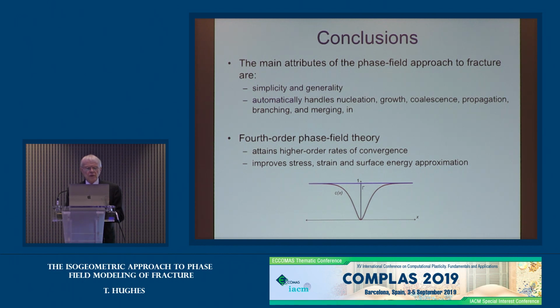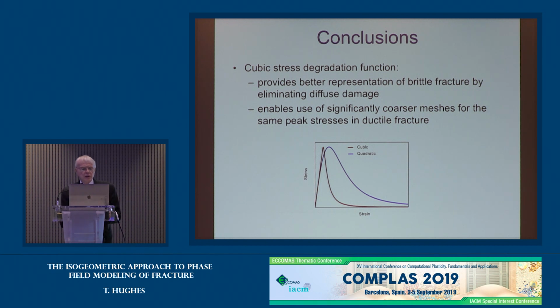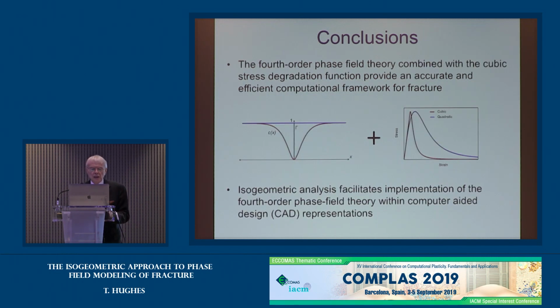The fourth order phase field theory attains higher rates of convergence than the second order theory, and thereby it improves the stress-strain and surface energy approximations. The cubic stress degradation function provides better representation of brittle fracture by eliminating diffuse damage, and it enables the use of significantly coarser meshes for the same peak stress as in ductile fracture. The combination of the two provides, I think, an accurate and efficient computational framework for fracture. And again, I'll emphasize it does converge to Griffith theory in the limit.